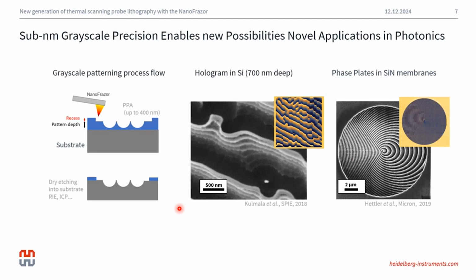Now, if we take the example of silicon, we can amplify the features from PPA downwards to silicon up to 10 times if we tune the etching recipe properly. If we're looking for an even higher amplification of the features, then you could think of introducing a very thick hard mask layer in between the PPA and the silicon, for example, thermal oxide, and then using a selective etching technique like RIE, you could amplify these features much more as well.